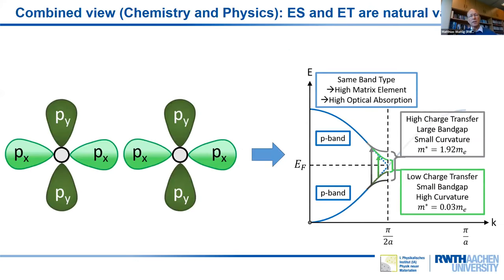I can also now draw this from the perspective of a chemist. We now make a sigma bond of these p orbitals. These p orbitals here are half filled. So there in total is one electron between these two atoms. And this should give rise to a metallic band. But then we have this band gap opening either via charge transfer, ET, or electron sharing, this Peierls distortion, ES, that opens a small gap. So we have a small gap.